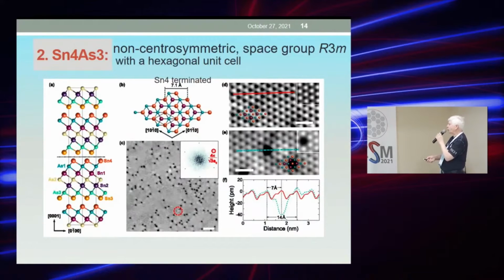Now, we move to a more interesting compound, which is made of the same elements, tin and arsenic, but it has a non-centrosymmetric structure and space group R3m with a hexagonal unit cell. There are actually several different positions of tin, which may be traced here. Therefore, the primitive lattice is rather large.